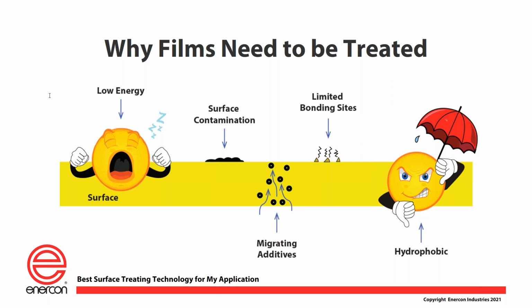And that's because plastic films, polyethylene, polypropylene, polyesters, things of that nature, they all have a relatively low surface energy or dyne value. Sometimes it's because of their inherent value. Sometimes it's because there are surface contaminants that come to the top. In my example of the bag, those contaminants usually are migrating additives, slip additives that come to the surface. And you might ask yourself, well, what are those there for? Why would the manufacturer put these additives in the product to make it slippery? Well, there are numerous reasons for that, but the main reason is they want you to be able to open the bag.